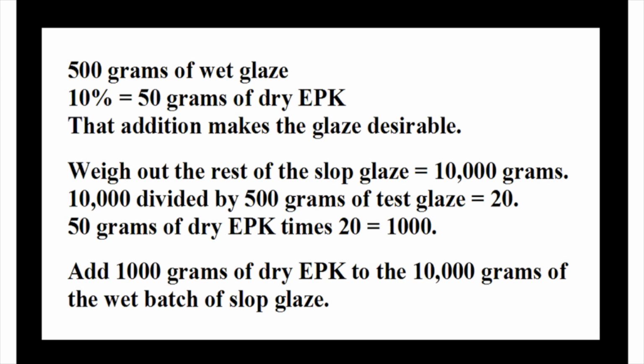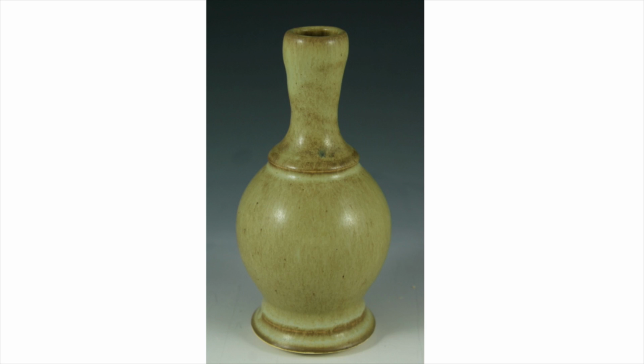So I multiplied the 50 grams that I needed to add to make it a workable glaze by that number: 50 times 20 equals 1,000 grams. I weighed out 1,000 grams of EPK and added it to the 10,000 grams of slop glaze, adding a little more water as necessary. This glaze should now relate and match the second stripe of the test tile. And so this is the bottle of the newly adjusted glaze.